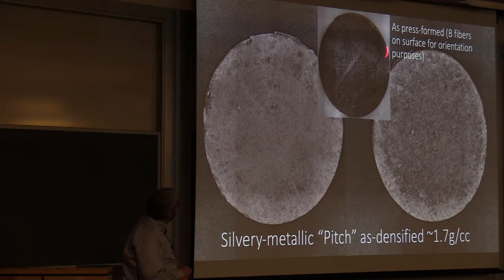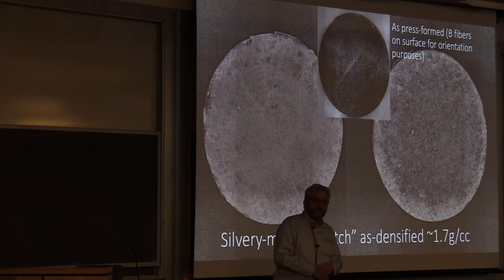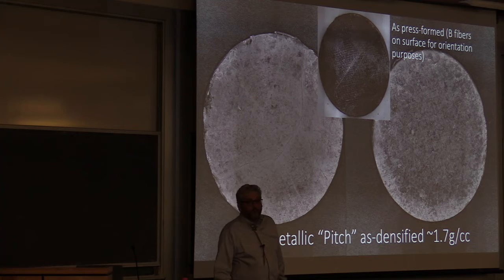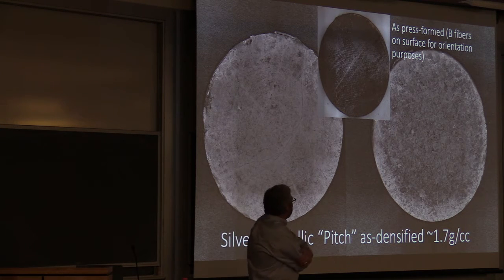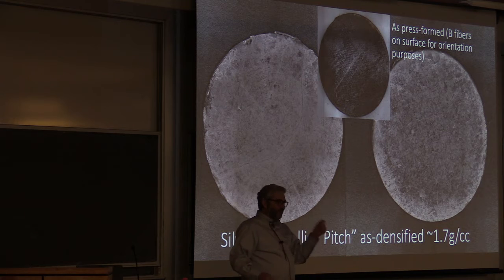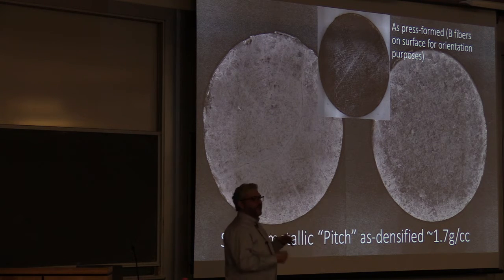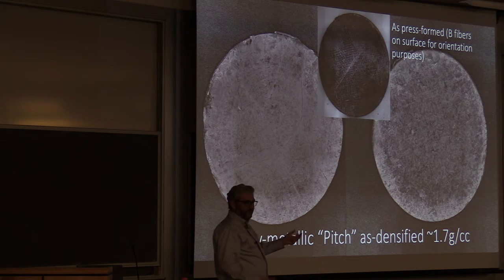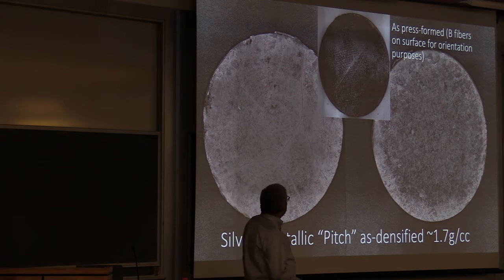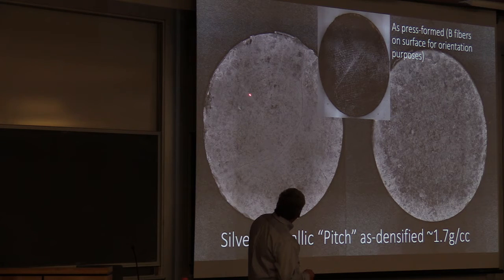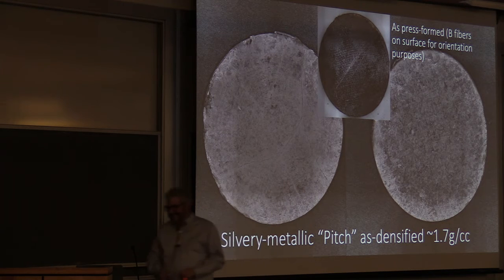Okay, so here's the part as built, as pressed, and then here's the part front and back after we did the densification. And you'll note that I didn't quite get to the 1.8 that was the target. This was the first experiment. Second experiment, I'm going to show you what we wanted to do. These lines right here are the boron fibers that I laid down manually so that I would know what the directionality was when I did my cross sections and saw where things were. And I can't find those when I look at this. What happened to them?